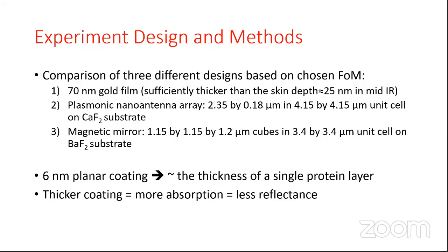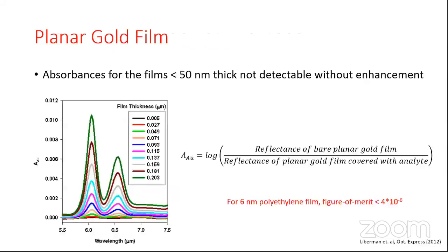And the polyethylene coating I chose is only 6 nanometer. So this corresponds to roughly the thickness of a single protein layer, because I know plasmonic nanoantenna arrays can capture even a single protein layer coating. But let's see what the magnetic mirror can do. We already know if the coating is thicker, there will be more absorption, which corresponds to less reflectance and higher figure of merit.